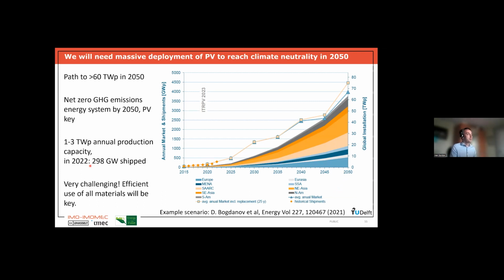So there are different models, but typically we can say, like in this model, that we probably need around 50 to 60 times more PV installed and operational than what we have today. So if we want to achieve 50 or 60 terawatt peak of PV modules by 2050, we only have 30 years left or even less. And that means that per year from now on, we should start producing 1 to 3 terawatt peak per year to actually achieve this 50 to 60 terawatt installed. Now in 2022, we have only made 250 to 300 gigawatt. So the exact number is not so clear, but we are far below what we need to install year by year to reach these numbers.